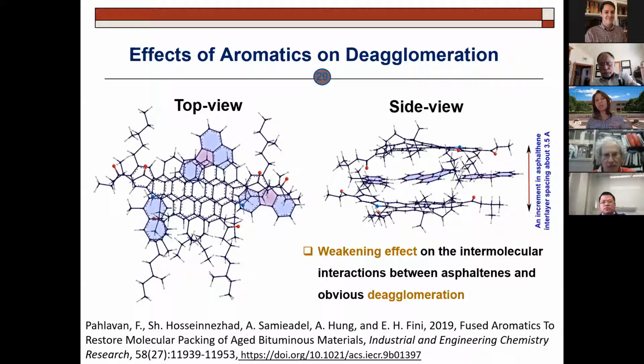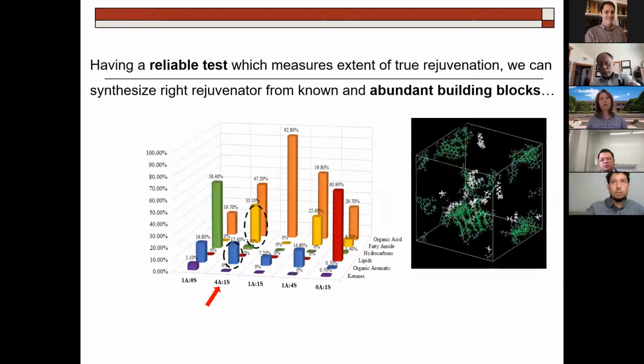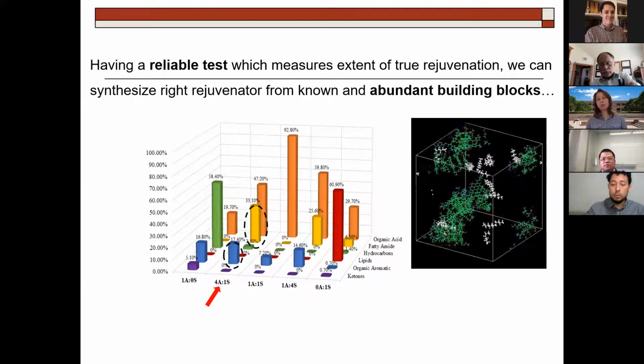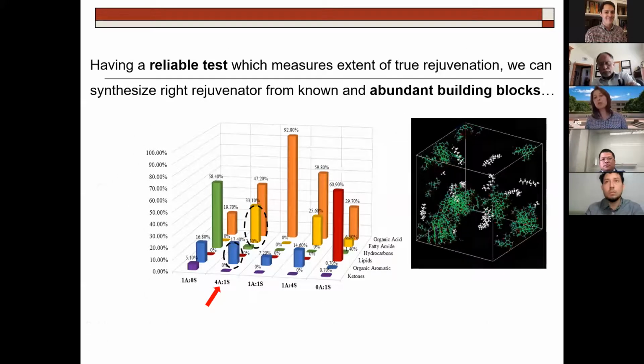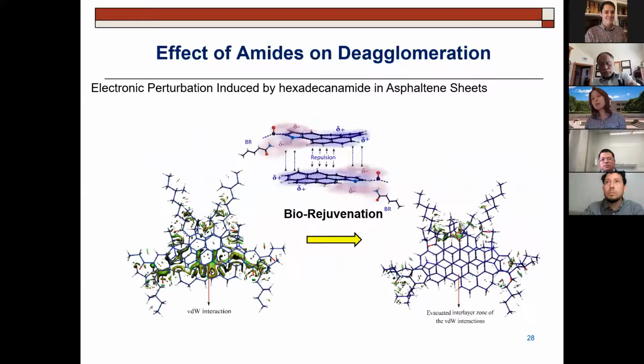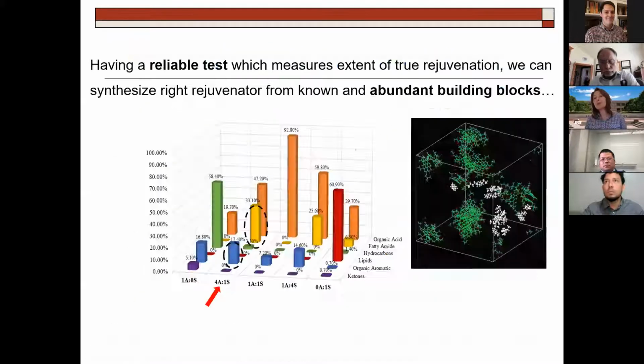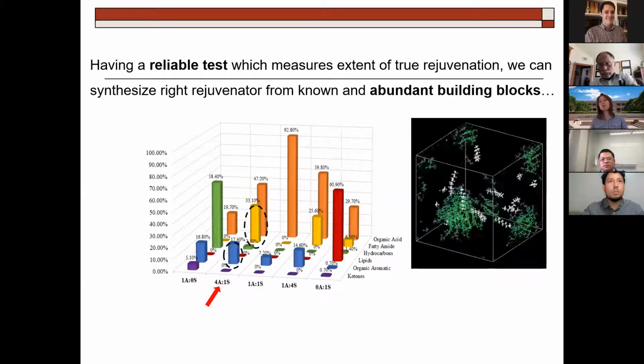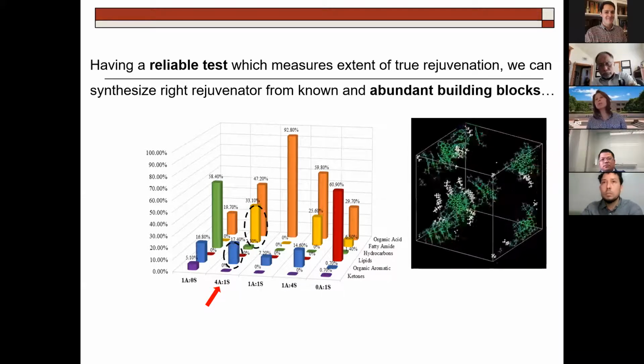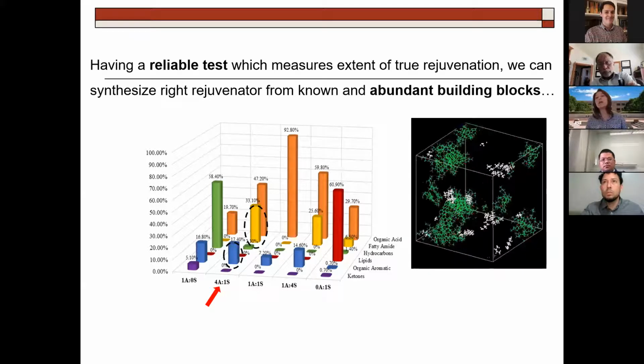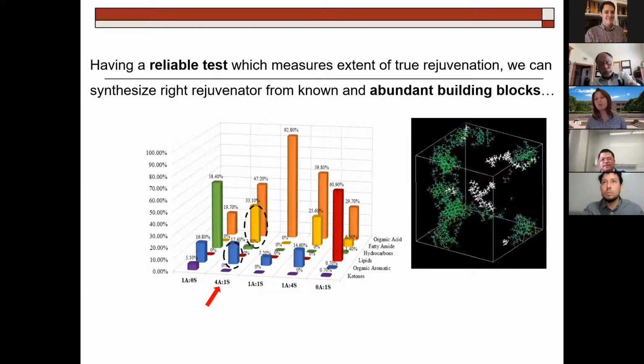The weakening effect is critical for a rejuvenator to work. If it cannot get inside, look at this rejuvenator, if it cannot get inside to push these two away, it would just be around it, like a liquid flowing around your asphaltene agglomerates. This molecular modeling shows you how this whole thing works with different molecules. I just showed you this molecule, for instance, gets in, this one gets in, but some of the alkane, for instance, doesn't. That's how it helps us formulate a rejuvenator that has maximum effect, because we got rid of the ones that cannot diffuse and added those that can diffuse into the agglomerates.